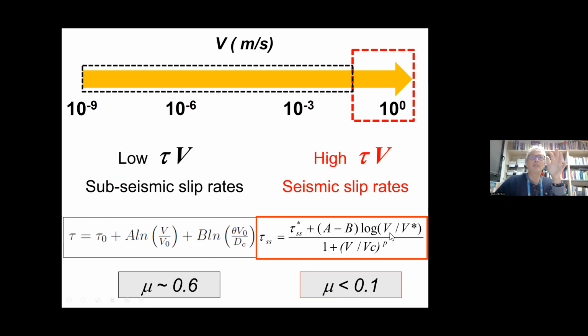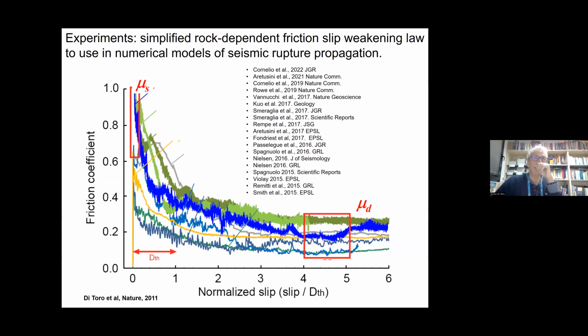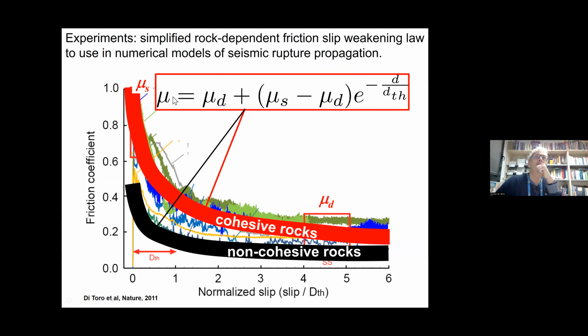But then you can also just make a best fit of the slip weakening decay. So now it's friction versus slip. These are many different rock types, and you can make a sort of slip weakening law. So we have a frictional coefficient, which depends on the dynamic friction, or residual friction during sliding at speeds of about 1 meter per second, and then this exponential decay, okay? So initial friction can be 0.8 and then a friction down here, and then there is some weakening distance that describes the decay.